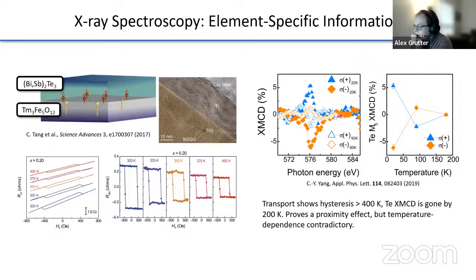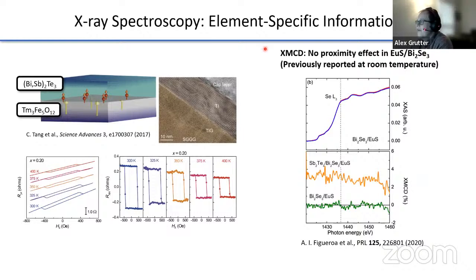So it's also an important side note that just because XMCD can't see it doesn't mean that there is absolutely no proximity effect, right? There could be a very, very small magnetization in the TI layer, and maybe it's just below the detection limit of XMCD, but not Hall data. It's kind of hard to know for sure. And the question of how magnetized it needs to be in order to give you a gap in the surface states is a complicated question. But I'll point out also that XMCD measurements on the well-studied europium sulfide bismuth selenide interface, with previously reported room temperature magnetic proximity effects, also find nothing in the bismuth selenide europium sulfide interface, which is interesting.